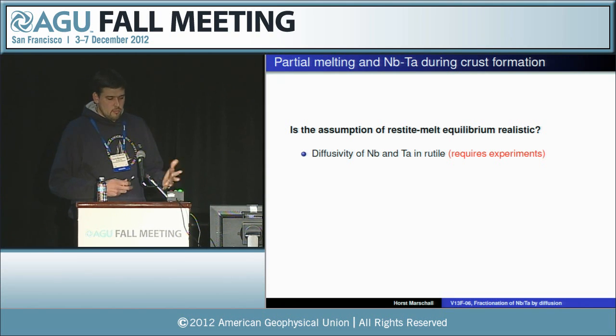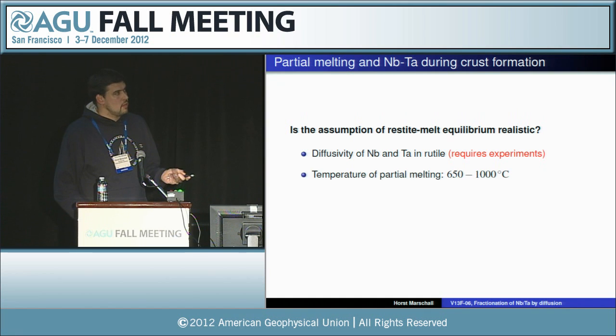And in order to address that, we need to look at the diffusivity of niobium and tantalum in the major mineral host, so in rutile. And that, of course, requires experiments. Then we need to look at temperatures of partial melting, and that may start at dehydration melting of muscovite or biotite and amphibole. That's what happens in partially melting crustal rocks in this kind of temperature range.